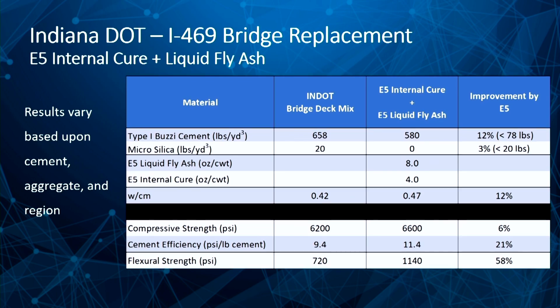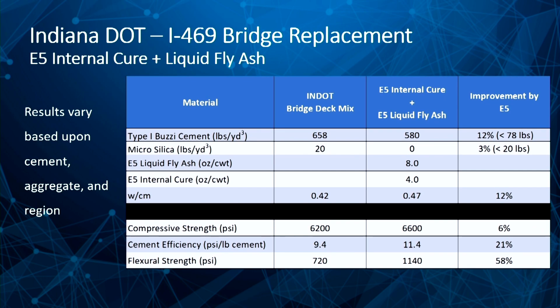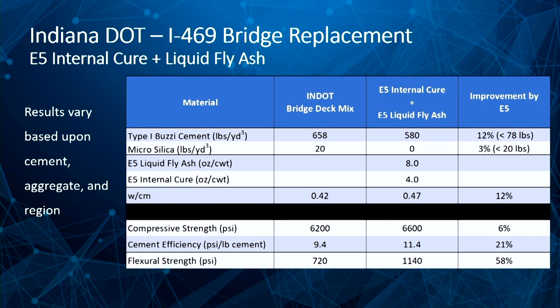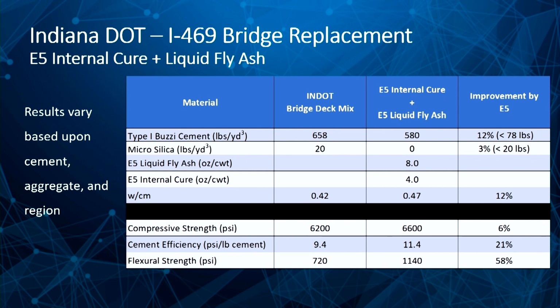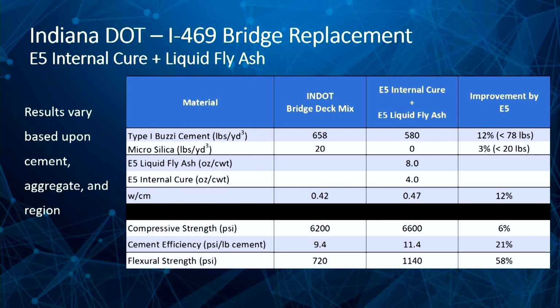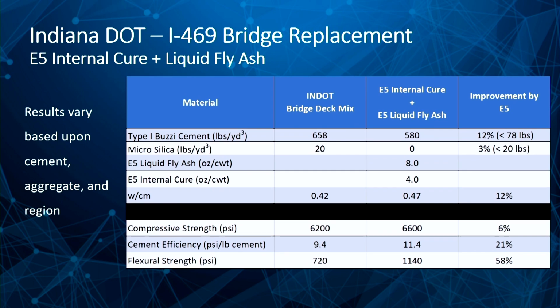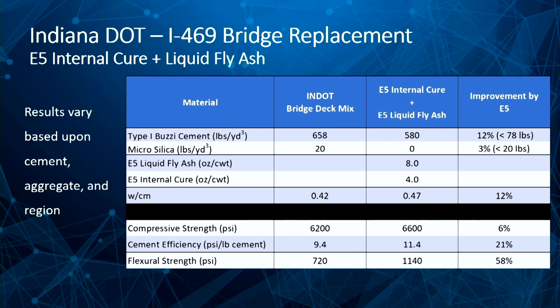So you can see here that we optimized the mix. We didn't just add these chemicals in there to try to increase strength. We dropped 78 pounds per cubic yard of cement, and we removed the microsilica, 20 pounds per cubic yard. So we've taken about 15% of the cementitious content out, and we increased the water to cement by 12%. So we've done some good on the materials.